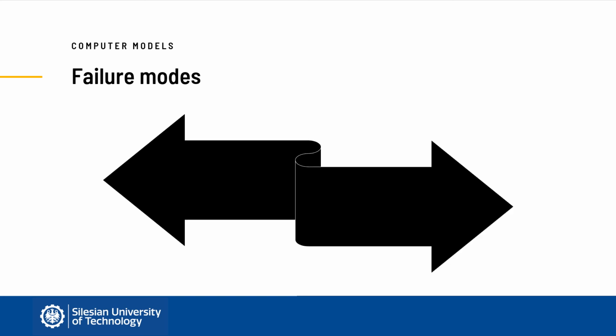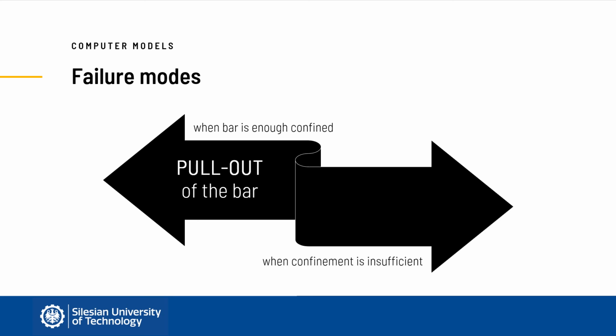The bond-slip law depends also on the mode of failure of the element under tension. When reinforcing bars have enough confinement provided by thick concrete cover or secondary reinforcement, the bar is pulled out of concrete volume. In an opposite situation, so when the confinement is insufficient, the element fails by splitting of the concrete cover.